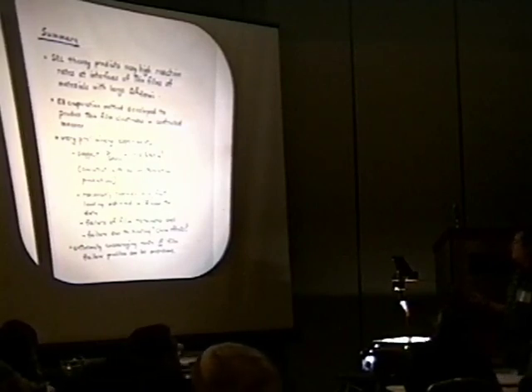The technique for developing these thin film electrodes has been developed and is fairly routine now, but still tricky to get decent surfaces to avoid excessive diffusion of the two materials together so you have a distinct interface and things of that nature. The experimental results that I've shown I would not class as anything but very preliminary, but they are suggestive of very high power densities in these thin films.